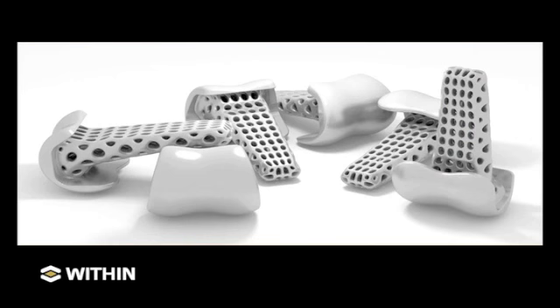So just to remind you, if you have a bone and you insert a solid metal implant into it, what tends to happen is the bone cells move away because they essentially sense that the implant itself can withstand the stresses, and so they don't need to be there. Nature knows that, okay, this bit seems pretty strong, I'll move away, I'll make myself porous. But essentially, they just start loosening the implant up, and the implant has to be replaced. And this is why hip implants and a lot of other implants, they actually won't give you until you're of an older age because your bones are constantly moving. And so if you're only in your 30s or 40s, they won't even give you those surgeries because they know it'll loosen up within 6 months.